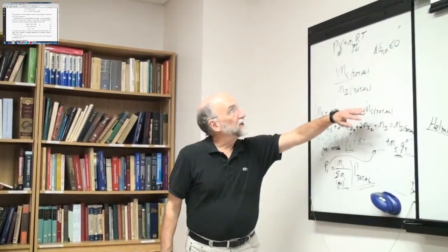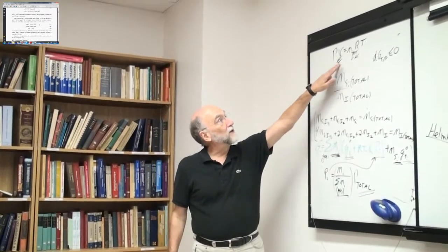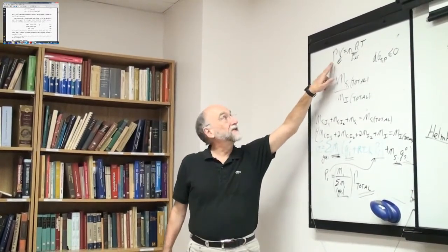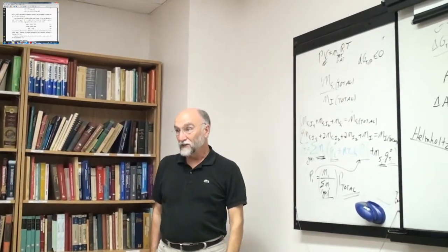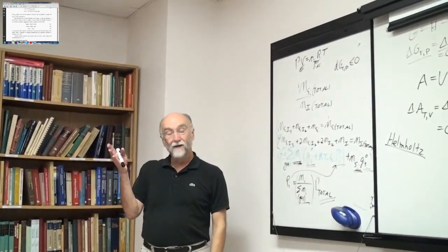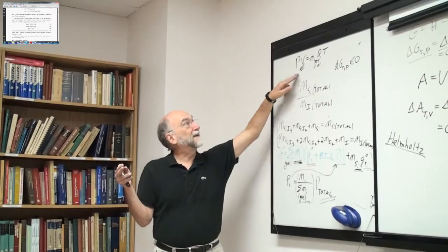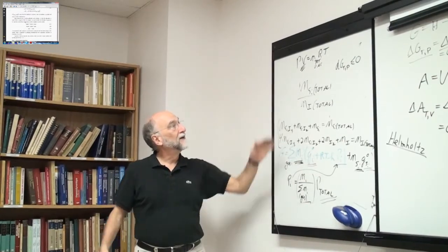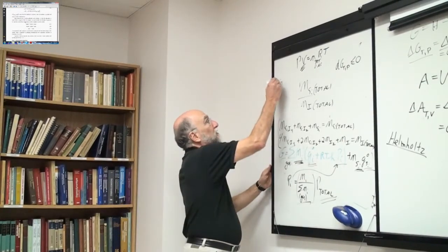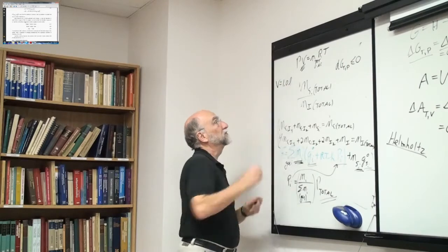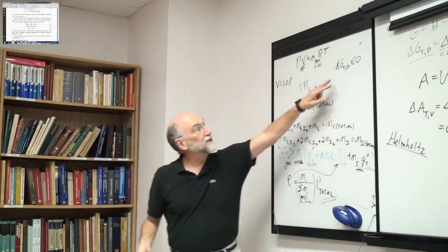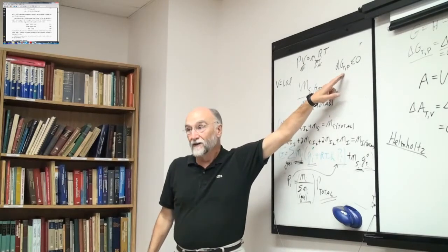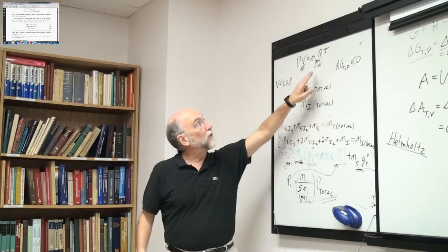So how do we do it? Well, the way FactSage does it is, if I tell it I want to do this at a constant volume, it guesses a pressure, minimizes the Gibbs energy at constant pressure until the whole thing's at equilibrium. Say I want volume equal to 1.0 liters. I guess a pressure of 1 atmosphere. I minimize the Gibbs energy at constant T and P. The system's now at equilibrium at 1 atmosphere.